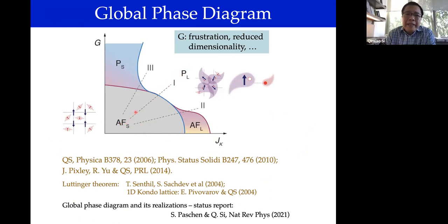This phase transition, which I just described for you, having the antiferromagnetic transition coincide with a large Fermi surface to small Fermi surface transition, represents one of the possible trajectories, or sequences of phase transitions, in the zero temperature limit. One could also have other sequences going through an antiferromagnetic order with a large Fermi surface, which becomes folded, or a paramagnetic phase with Kondo destruction. This would have several stages of phase transition in the zero temperature limit. But what I have focused on so far, and what I will focus on primarily in the remainder of the talk, is this trajectory one.